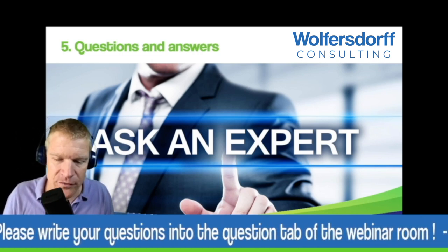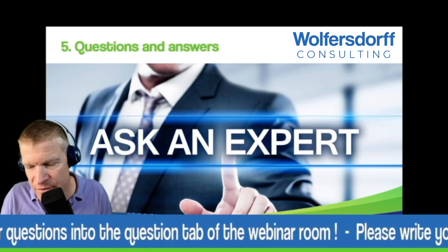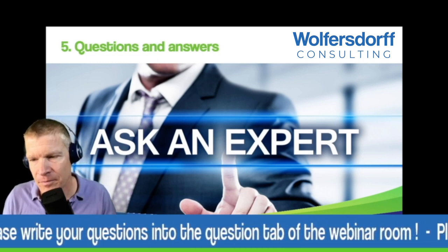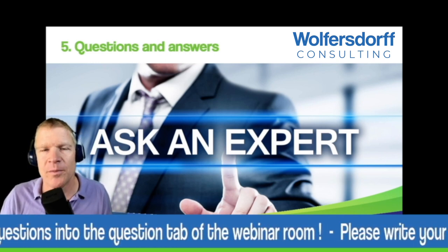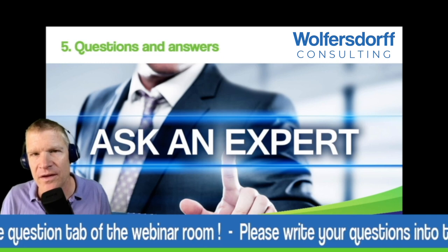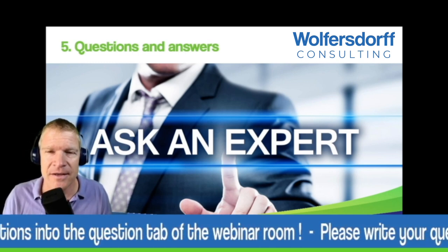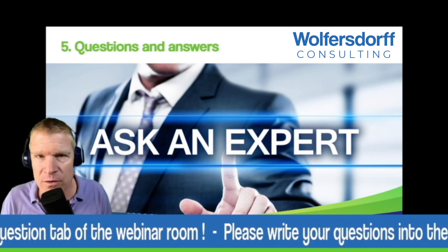And the last question, also from Derek, do you have data that you can share about the carbon dioxide savings from using RCB? Now, I quoted the masterbatch companies and the carbon dioxide saving they advertise. You might understand that the carbon dioxide burden of the recovered carbon black also depends on the thermal efficiency of the process. So what I see, if you have a batch discontinuous process, I see values of 0.4 tons carbon dioxide per ton of recovered carbon black, which is already 2 tons less than the virgin carbon black. And I see 0.2 tons of carbon dioxide burden in the case of continuous processes.